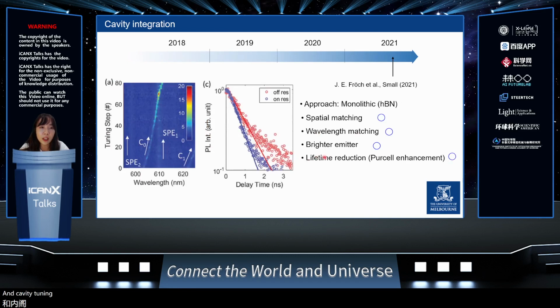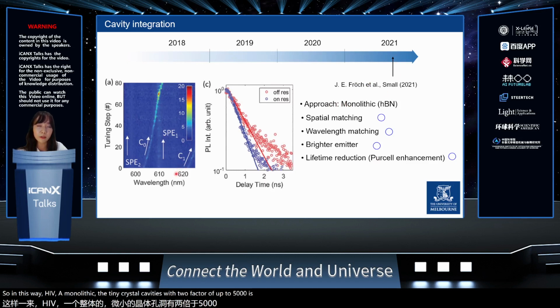Cavity tuning and lifetime reduction were very recently demonstrated, at the end of last year. In this work, hBN monolithic photonic crystal cavities with a Q factor of up to 5,000 are employed. To couple the single photon emitter to the cavity resonance, the method that we used is the gas condensation tuning approach. For this purpose, ambient air was delivered to the cavity at cryogenic temperature. This increases the effective size of the resonator and causes the cavity mode, C0, to redshift. We were able to tune the wavelength of C0 by up to 10 nanometers in this effort.